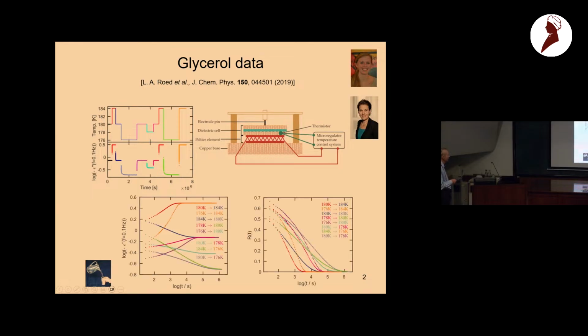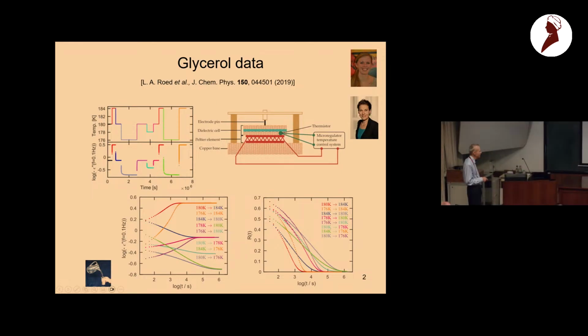Here we plot the same data as function of log time. This was linear time after the initiation of the jump. And of course we end up in equilibrium. This is I think the jump to the lowest temperature, and so on, different jumps, and they end up equilibrating depending on what is the final temperature. The next thing we do is we introduce a normalized relaxation function. So you basically normalize this so that it starts in unity. And we cannot see this start because it's too rapid in our experiment. So that's why we start here. So these are the normalized relaxation functions.